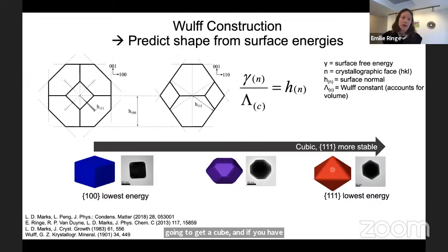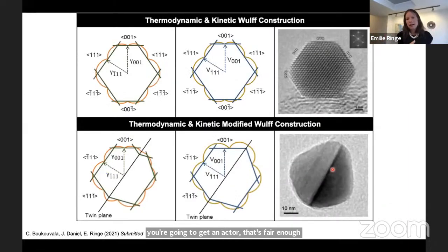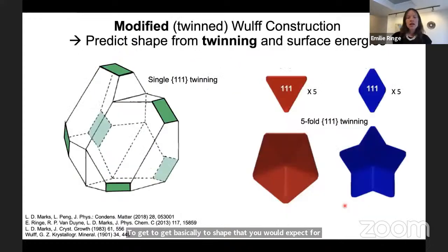Well, that's fair enough. You can modify this to get basically a twinned Wulff construction, where you basically, very simply, just create two Wulff constructions of two twins split by the twin plane, and you stick them together numerically to get basically the shape that you would expect for something that has a twin.